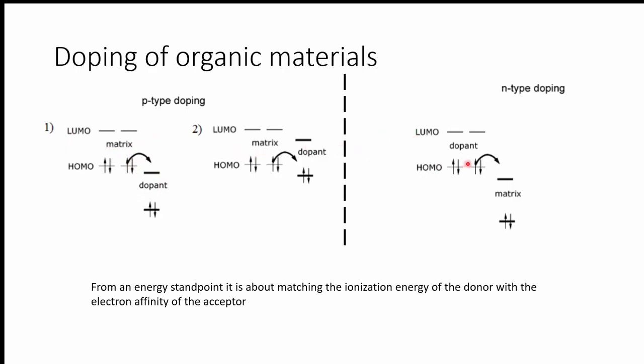Now, on the other hand, if you have an electron poor polymer, which is represented here, what can happen is that you can get a transfer of electron from the dopant into the matrix so that you fill the unoccupied orbital, and then this single electron that you just added can jump around inside your system.